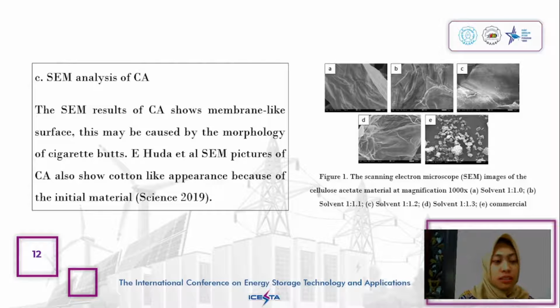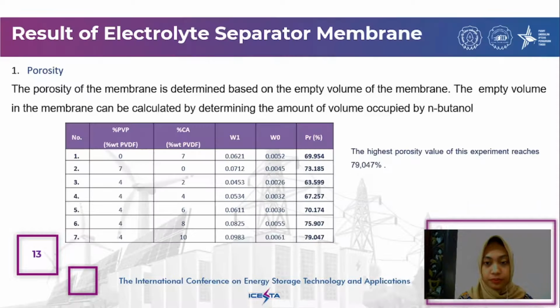This is the result of SEM analysis of cellulose acetate. The result shows that CA has a membrane-like surface morphology, and this may be caused by the morphology of cigarette butts. For the results of the electrolyte membrane separator, the first is porosity. The porosity of the membrane is determined based on the empty volume of the membrane. The empty volume in the membrane can be calculated by determining the volume occupied by N-butanol. And the highest porosity value of this experiment reaches 79.047%.